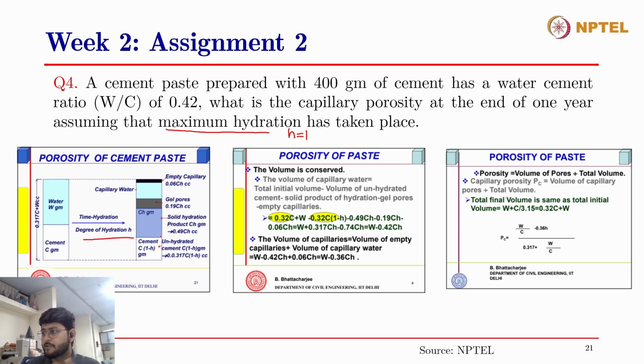But here in the question it has been mentioned that maximum hydration has already taken place. That means that H is 1. Now if H is 1, there is no unhydrated cement left, because C into (1 minus 1) will give you 0. So all the cement has already hydrated. So you'll have essentially in the final system solid hydration products, gel pores, and capillary water and empty capillary pores, right? In any other given system where the degree of hydration is, let's say, H, in the final system you'll have some amount of unhydrated cement, that is C into (1 minus H) grams. Then you'll have, let's say, CH grams of solid hydration product. Then the volume occupied by the CH grams of solid hydration product will give you 0.49 CH centimeter cube.